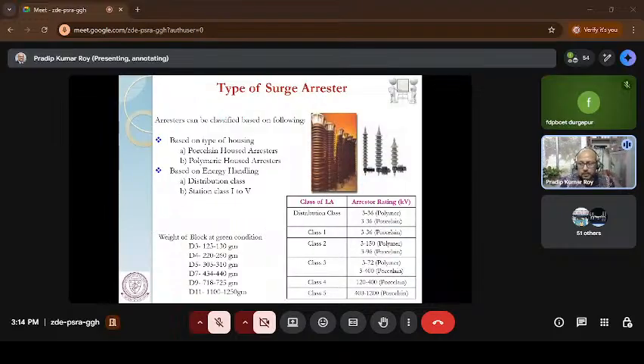Now, if you look at the classification of the surge arrestor, there are two major classifications based on housing. One is insulator based, and the second is rubber based, which is basically polymer. Mostly in polymer based, the products are of small rating, hardly around 72 to 100 kV surge arrestors are available. But in porcelain based surge arrestors, it can go up to 1200 kV also. Earlier it was 400 to 800, but now people are talking about a 1200 kV surge arrestor because we have developed a 1200 kV transformer, and to protect that transformer we need a 1200 kV surge arrestor as well.